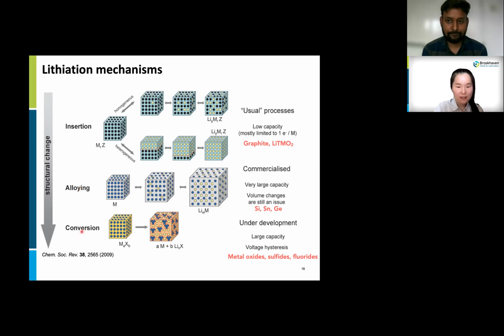In the conversion reaction, multiple lithium ions are also participating, and we can get huge capacity. This kind of material is usually a metallic compound like metal oxides, sulfides, or fluorides, and by reacting with lithium, lithium compounds and metallic nanoparticles are formed. This mechanism still needs a lot of investigation because of voltage hysteresis and capacity fade.